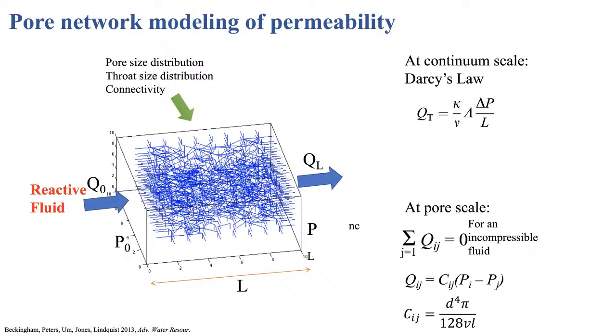So we can define a system of pores and some kind of lattice. We can use information on pore and throat size distribution and connectivity for the specific sample we're interested in. We can have a reactive fluid flowing through the system. We can solve for the pressure in each node. And then at the continuum scale, apply Darcy's law and get permeability.